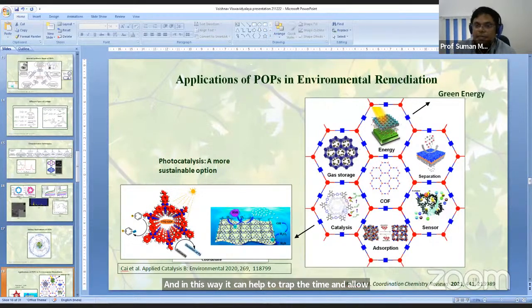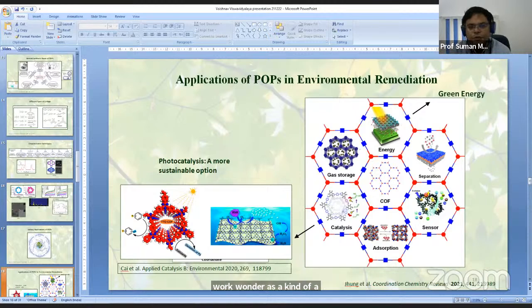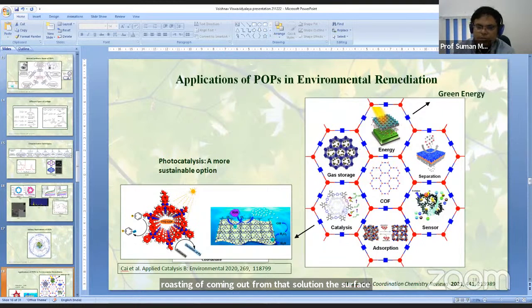And in this way, it can work wonders as a kind of molecular sieve, to stop the rose Bengal coming out from the solution. The surface area of this covalent organic framework is found to be about 800 meters square per gram, and the pore size is something about 2 nanometer in diameter.